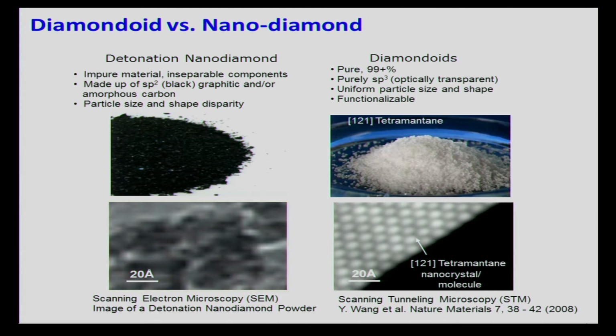And if you take a microscopic look at these two species, this is under TEM, this is under STM, what you see is that with the nanodiamond, the diamond by detonation, you have really a wax-like mixture of different species. With the diamondoid we found in the oil, you can see that each of these bright dots represents one single molecule of diamond sitting on the surface. They're really, really pure and really uniform. This is something that nobody was able to have before, and now we have them in large quantities and large varieties, and this really gives us a very exciting playground to explore some of their applications and properties.